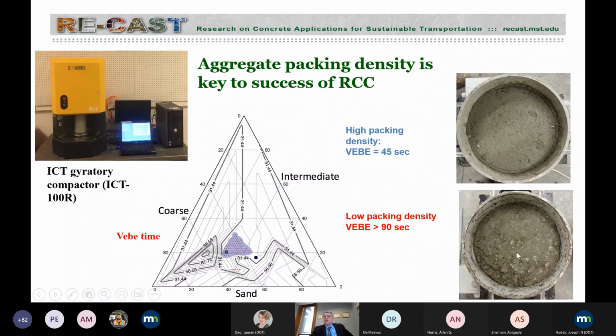This is after consolidation using the VB test. And we could see that the VB time is greater than 90 seconds. And if it's that long, we just stop the test. And if we use this region with high packing density, we see the VB test is about 45 seconds. I'm saying all this because these numbers will come back when we look at the two case studies where RCC was used.